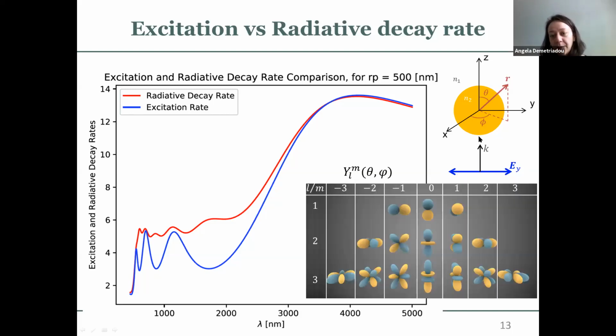structure. And by choosing a Y polarized plane wave, what I'm basically choosing is the M equals -1 in this case. So this is a set of the spherical vector harmonics. And by choosing this polarization incident onto a spherical nanoparticle, I'm basically choosing only these ones. I'm doing a selection on which spherical harmonics I'm picking because of my polarization and the wave vector direction.